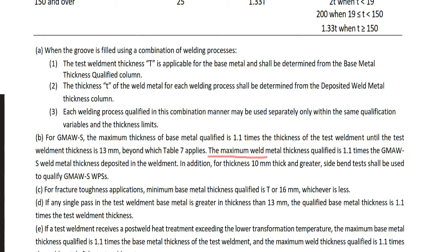The maximum weld metal thickness qualified is 1.1 times the GMAWS weld metal thickness deposited in the weldment. In addition, for thickness 10 millimeter and greater, side bend test shall be used to qualify GMAWS WPSs.